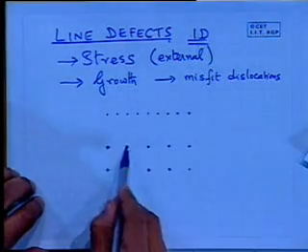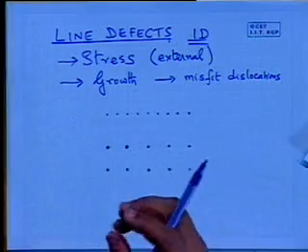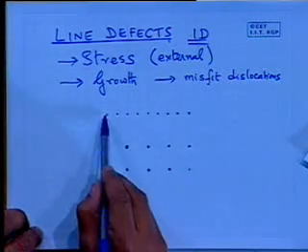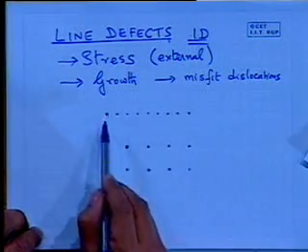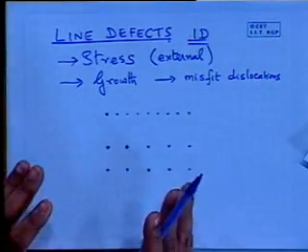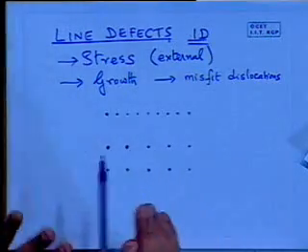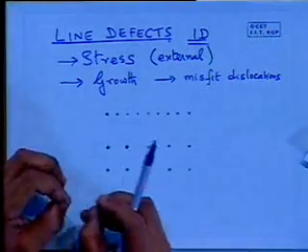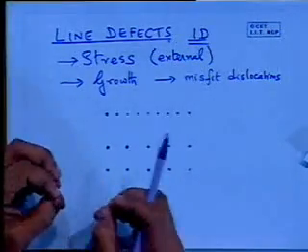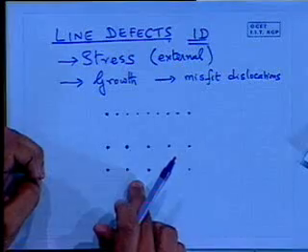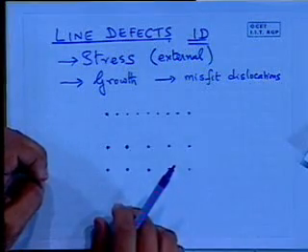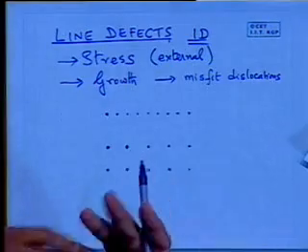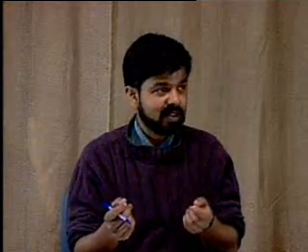Here the atoms want to sit this far apart, and then I'm going to try to put something on it where the atoms want to sit this far apart. I'm going to generate stresses there. And up to a point, known as a critical thickness, this crystal will accommodate and change its dimension. The lattice constant will change. Why will this not change very much? Because this is bulk. It's harder to deform something that is thicker than something that is very thin. So my film will